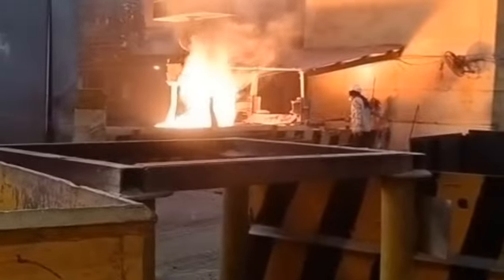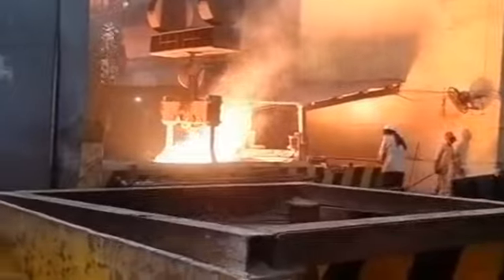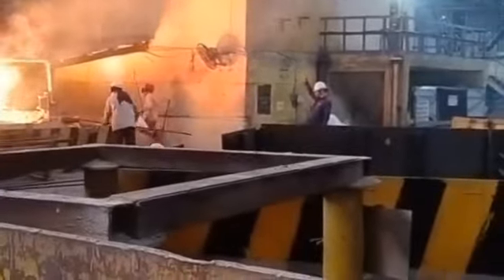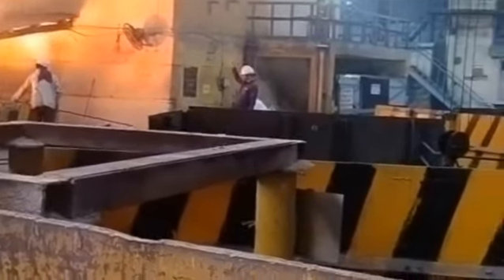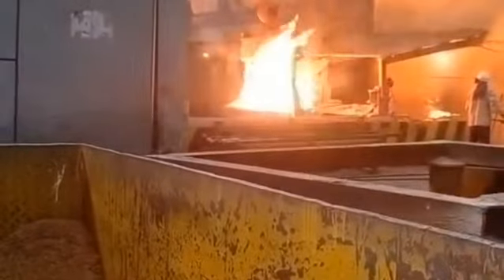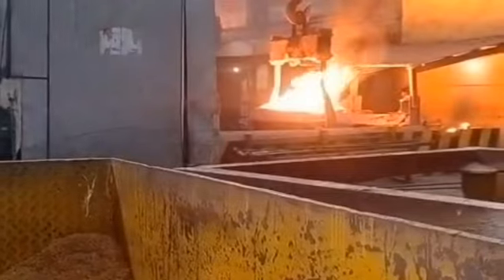Third process is melting of scrap. Brief procedure. The electrodes are lowered. On supplying the necessary current and voltage, an arc is struck between the electrodes and the charge for 45 to 55 minutes. The gap between the electrodes and the charge is maintained by regulating the movements of the electrodes so that the arc remains between them. After 45 to 55 minutes, oxygen lancing pipe is used for cutting of scrap through the slag door. The temperature during this procedure is 1650 to 1700 degrees Celsius.